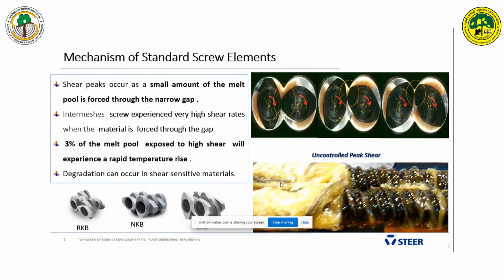The input material is white in color. Finally, after compounding, you are getting the degraded polymer in the metering section. Degradation occurs in many shear-sensitive materials like PVC, and also sensitive materials like wood composites, like bamboo, and many others, even biodegradable polymers like PBAT and PLA, which are very sensitive to shear. It degrades and liberates black specks, and that is of no use at all. Once you compound a degraded polymer, you cannot make a product out of that.